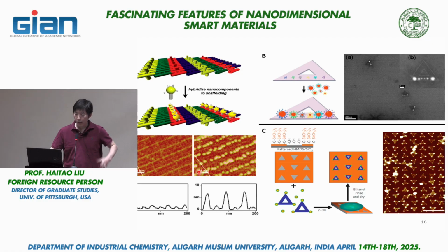Okay. There are other forms of this. I want to highlight this one. This is a case where different size quantum dots are being anchored onto a triangle-shaped DNA structure. And each quantum dot has a DNA strand modification. You may notice in the cartoon here, on the triangle DNA structure, each location has been modified with additional DNA anchor strands. So once you put everything together, you will see this, this is the SEM image.